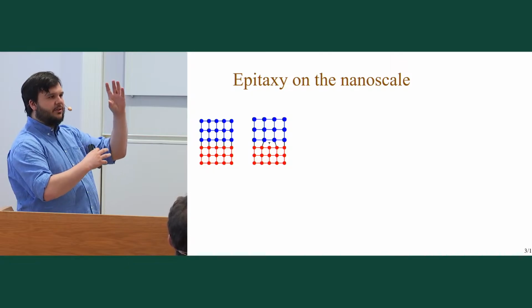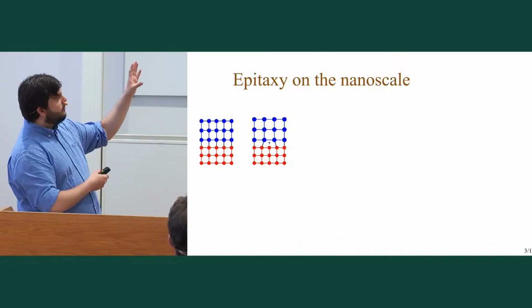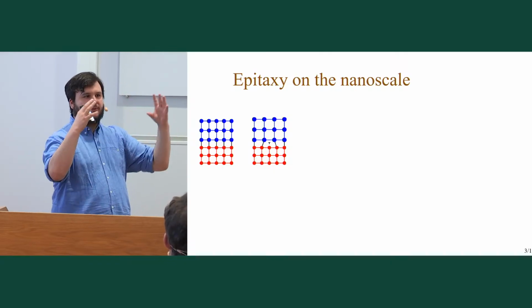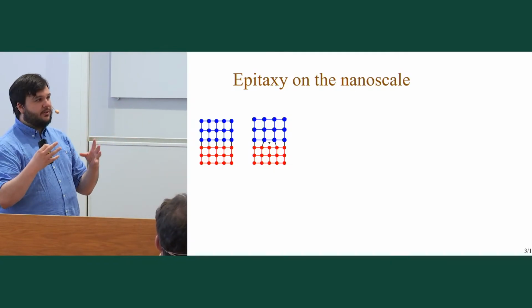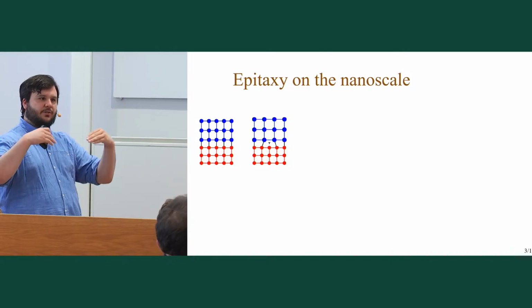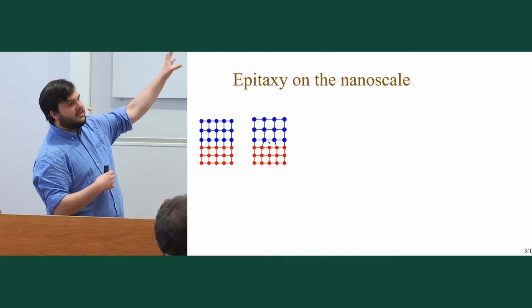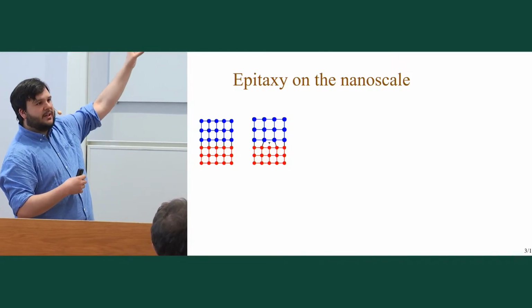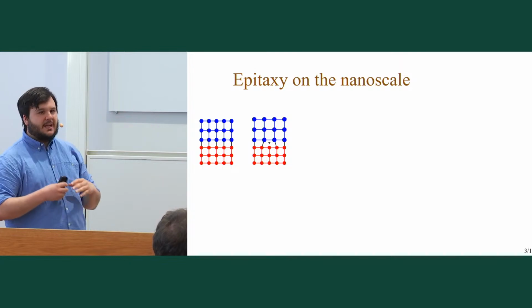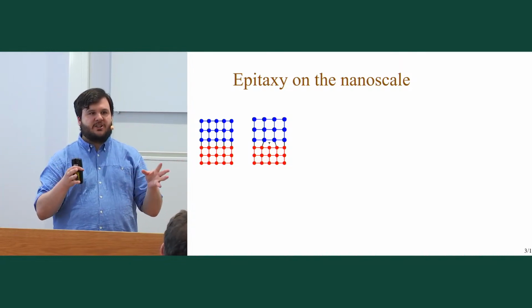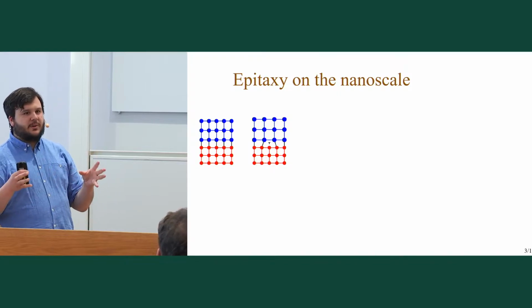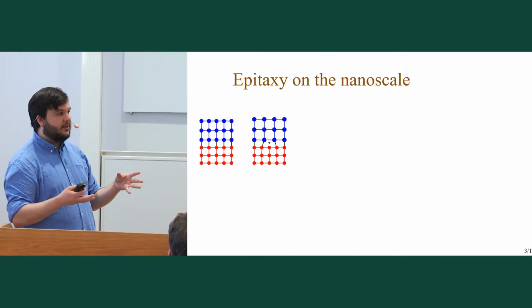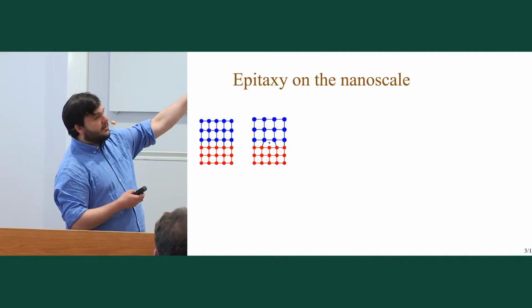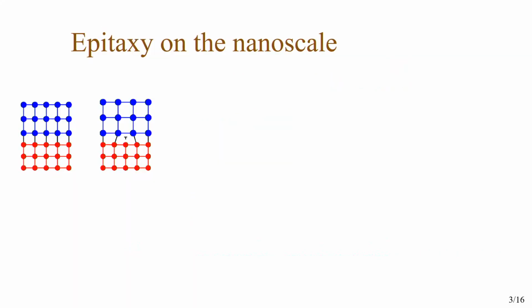So when you combine materials, there's a technique called epitaxy, which comes from the Greek, which is essentially how you deposit a crystal on top of another. We have the blue material, which is the material we're trying to grow, on top of the red material. If these are two good crystals, the blue material will adopt the same structure as the one below. If we see each dot here as an atom, then you see that the blue layer conforms to the bottom layer. However, this only works if the atomic arrangement is very similar. If you have a very different atomic arrangement, you'll start to introduce so-called defects, misfit dislocations and other types of defects, as we see there on the right. Now, one way to avoid this is to make the interface areas very small.